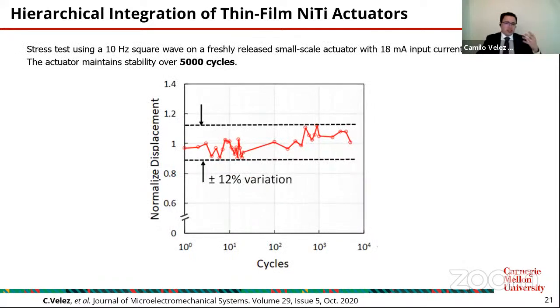Some of the questions that we had from reviewers at some point were, wait, but it's 3D printed, it's just a prototype. Yes, but it's a prototype that can work up to 5,000 cycles. We tested these for 5,000 cycles with a variation of less than 12%. So for prototyping purposes and university purposes, it's a very robust technique.